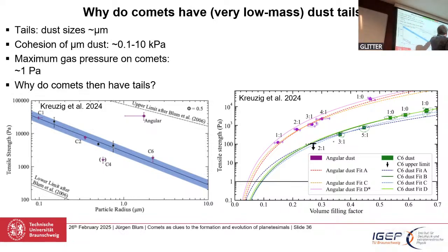So this is some work from my lab from last year, as a function of the volume filling factor, 1 minus porosity. We measured the cohesion inside, and as I mentioned before, Josep Maria has measured the tensile strength of cometary origin meteor showers, and the canonical value is in the kilopascal, which matches very well with what we're finding here. And as a function of grain size, we find that kilopascal is here. So if it was a kilopascal at 50% porosity, we would have grain sizes of a few microns. At 10 kilopascal, they could be 100 nanometers. This is the range we're talking about. So we have cohesion on the order of kilopascal.